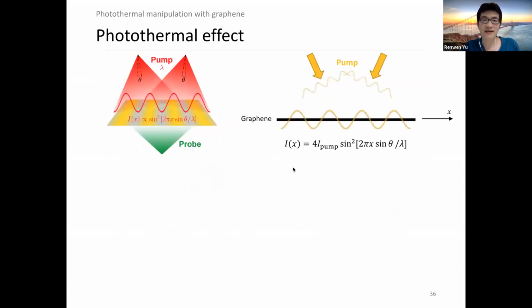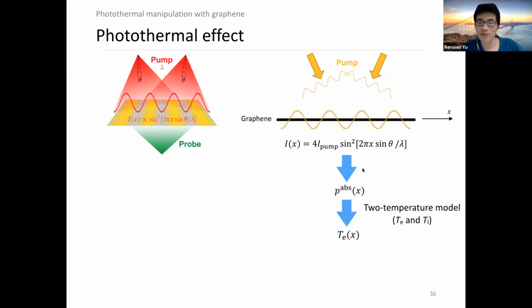So following this line, we think about something interesting. Basically here, we have assumed there are two pump beams coming from the far field, and they create interference patterns onto the graphene plane. And the light intensity on the graphene plane can be given in this expression, which of course depends on the spatial coordinate x. Due to this light intensity distribution, we can have absorption power density of light in the graphene plane. And from this absorption power density, we can calculate the elevated electron temperature as a function of x. And then we can have a periodical spatial distribution of optical conductivity of graphene just by optical pumping.